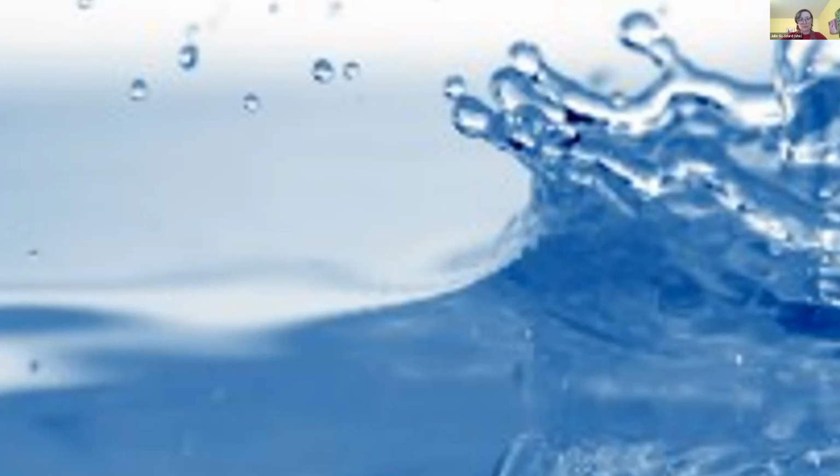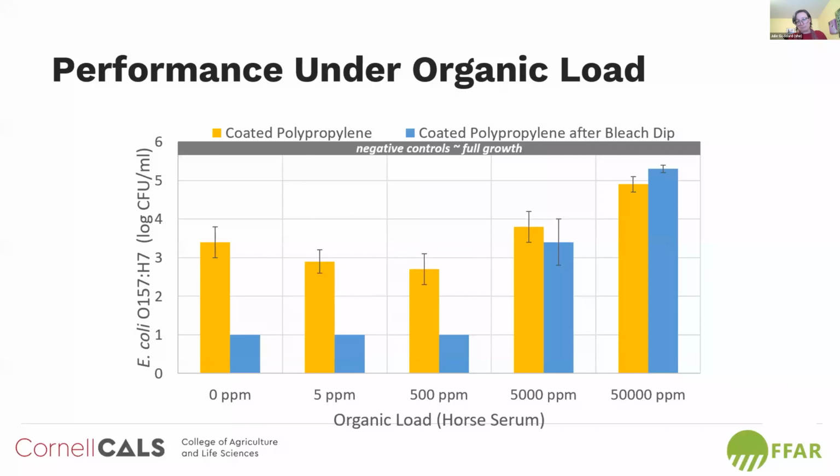But it's absolutely essential because in reality, materials are less likely to be exposed to this and are more likely experiencing something like this, right? Waste streams or food products full of complex constituents like dirt, proteins, et cetera, across a wide range of pH values with the introduction of alkaline detergents and acid sanitizers. So while it's important to start your proof of principle studies, as we did, using a standard commonly used method, it's also important to challenge the material in the presence of organic matter.